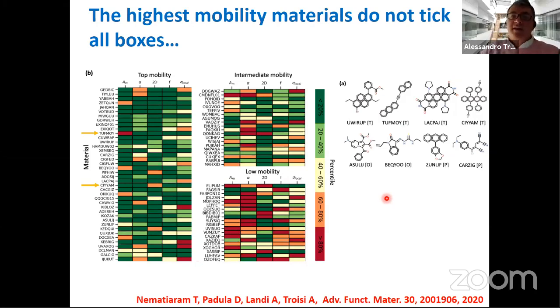Maybe I would like to make just one point slowly before going to the conclusion. Once you look at the data set, these are a few examples of high-performance molecules. Possibly the most important discovery of this high-throughput screening is that the best materials don't tick all the boxes. So if you look at the top mobility materials, and we color in green if one particular property is ideal, and in yellow or red if it's not ideal, we realize that the top materials are not ideal with respect to all possible properties. This means that there is room for improvement, and you can actually use the data set to decide what is the maximum achievable mobility for this set of materials.